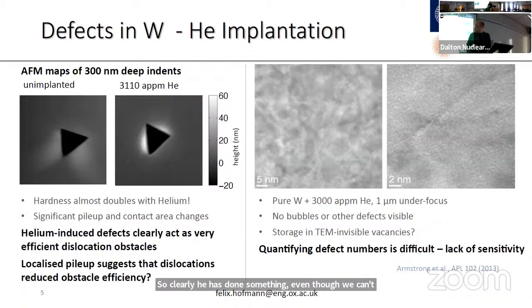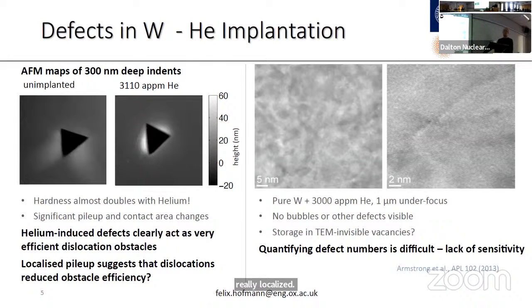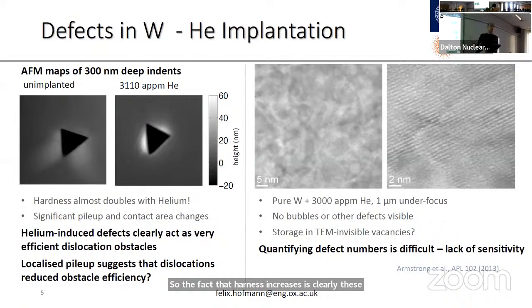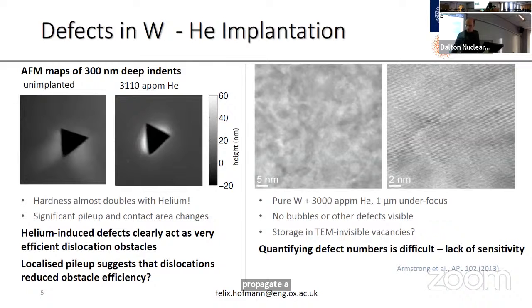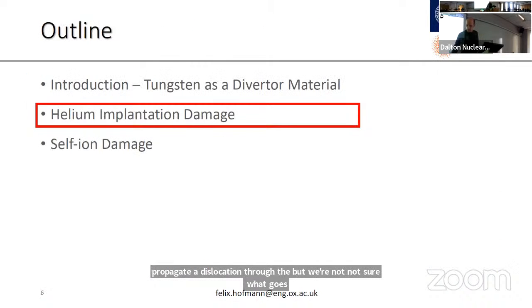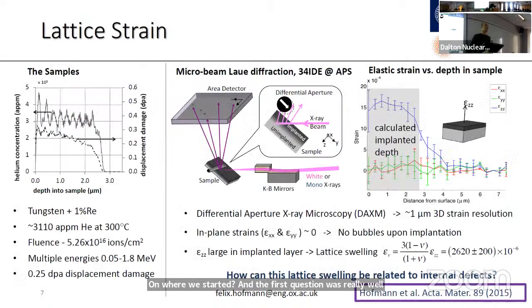And you also see that in this case you've got this really localized pileup. So the fact that hardness increases says clearly these helium defects are quite good obstacles to glide dislocations. And this localized pileup suggests that maybe the material becomes softer when you propagate a dislocation through, but we're not quite sure what goes on. So anyway, this is where we started. And the first question was really, how can we quantify the number density of these defects?